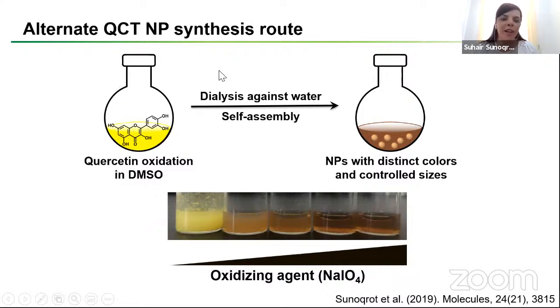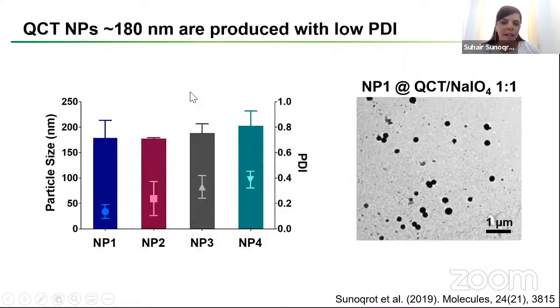And then we also tried a third approach, and we wanted to see if we oxidize quercetin using an oxidizing agent and dialyze the solution, will it form nanoparticles? In this case, we tested the oxidizing agent sodium periodate, and we incubate the quercetin with increasing amounts of this oxidizing agent. And indeed, we were able to obtain nanoparticles with a range of colors. As we increase the ratio of the oxidizing agent, they become darker and darker, from light brown to dark brown in color. And interestingly, the size was even bigger.